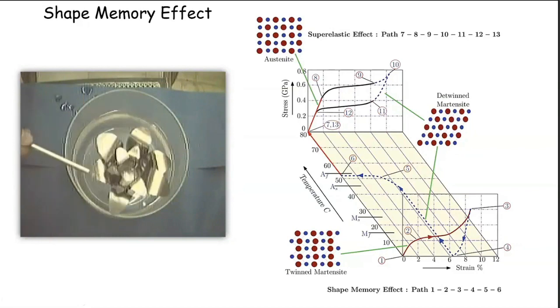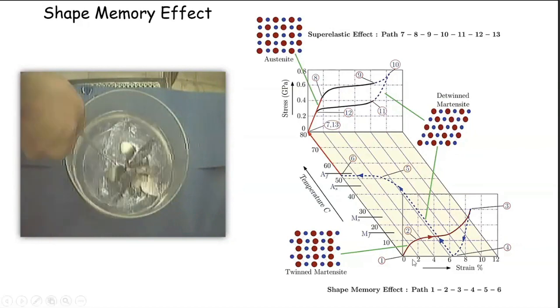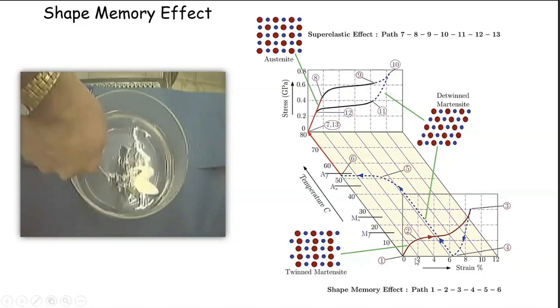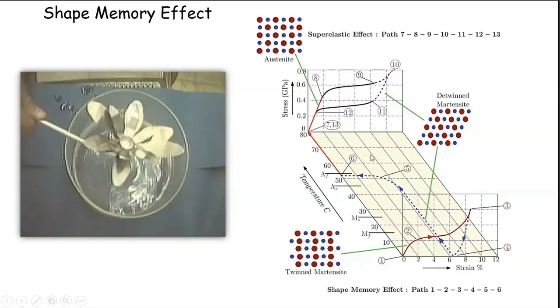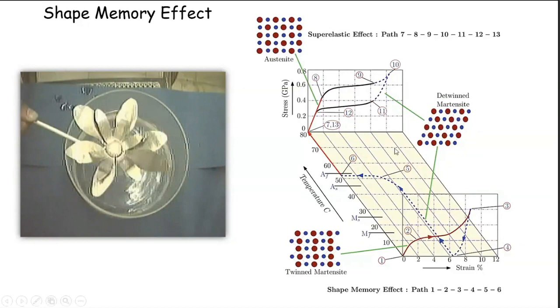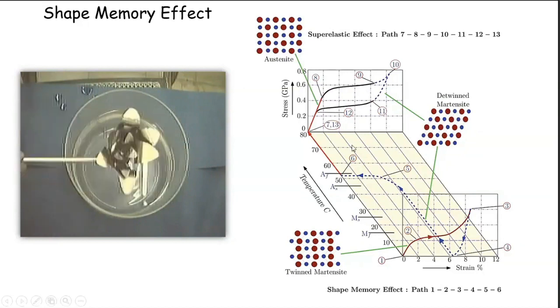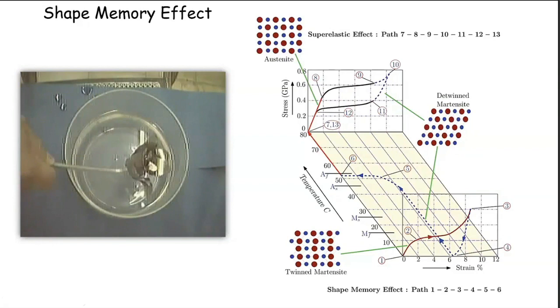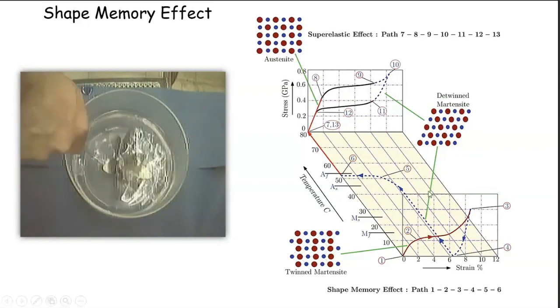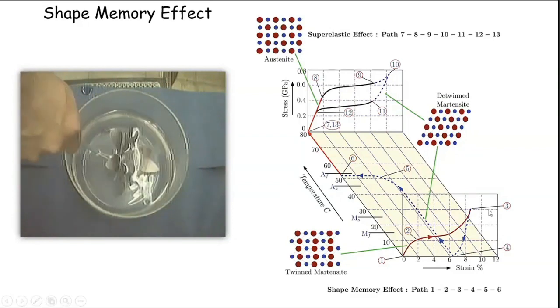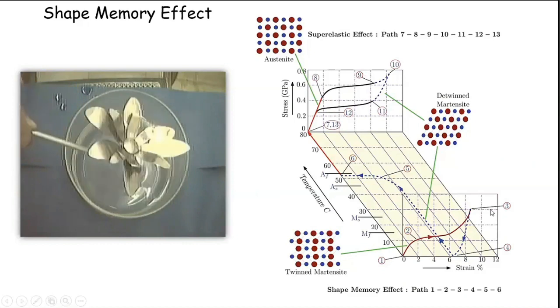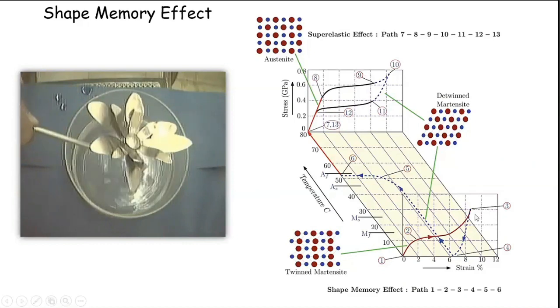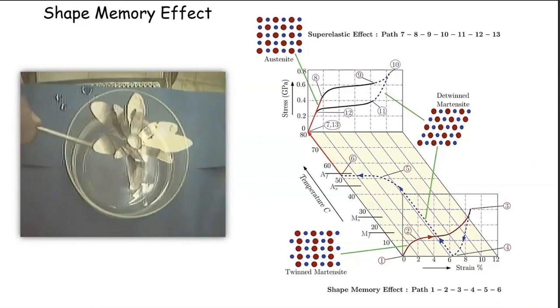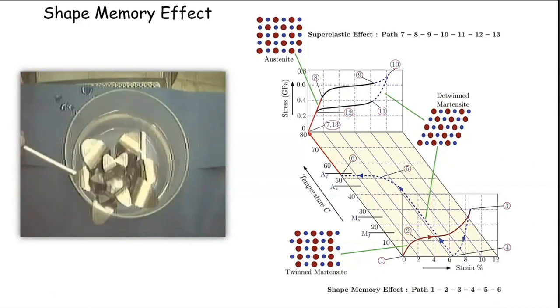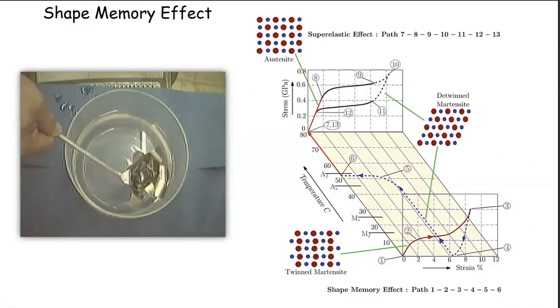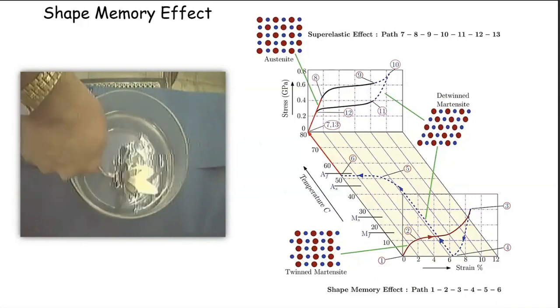And as it happens, at room temperature it's in one crystal structure, and when you heat it, it is this reverse martensite to austenite transformation that restores its original shape. So you have a phase transformation that is responsible for restoring its original shape. So in the martensitic condition, unlike what we experience in other kinds of alloys, it is very soft and pliable. So there are mechanisms of deformation which we can quite understand, that it won't be the conventional plastic deformation where you have shear with some dissipation aided by dislocation.